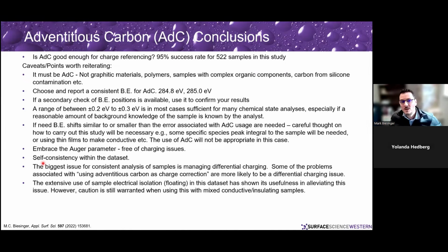The biggest issue that we found for samples, the 5% that failed, was differential charging. So it's not necessarily a failure of the adventitious carbon, it's a failure of our ability to either mount those samples isolated or make them behave properly, where if you change things, things are moving around. Differential charging was the biggest problem. And sometimes that's just something that can't be avoided, if you can't ground or you can't float the sample, or there are other issues like that. So that was the biggest problem that we found.